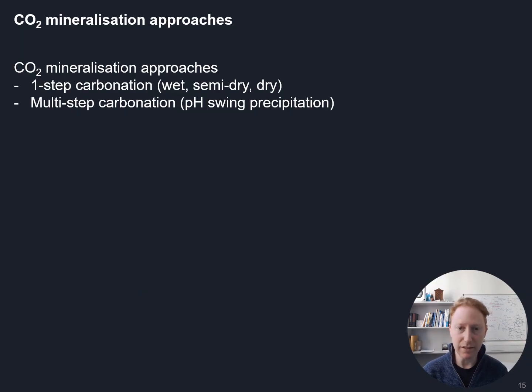Now let's consider the CO₂ mineralization approaches that we could take. We could either apply one-step carbonation, which means doing the carbonation in one reaction. This can be done in a wet process, in a humid environment, or in a dry environment. On the other hand, we could go through a two or more step carbonation process, and this is usually done by pH swing precipitation followed by subsequent liquid-solid separation processes like filtration.